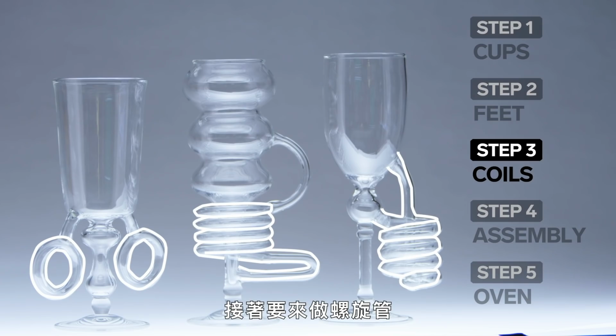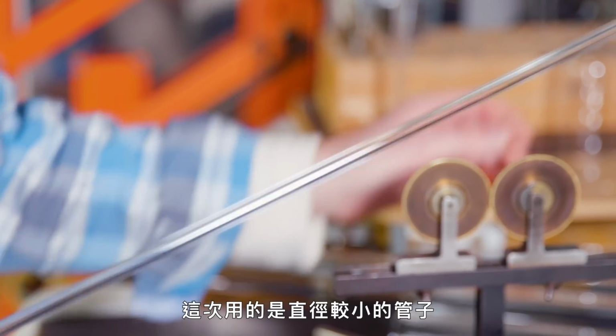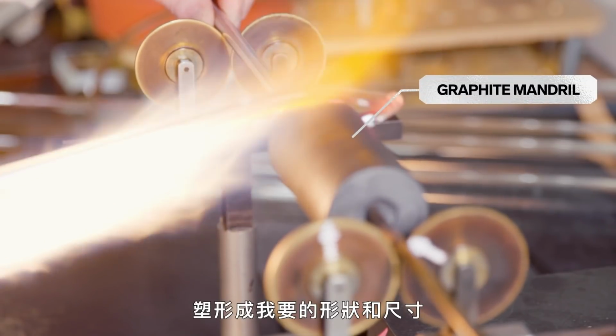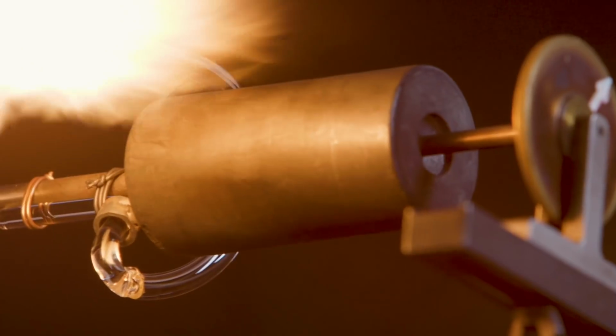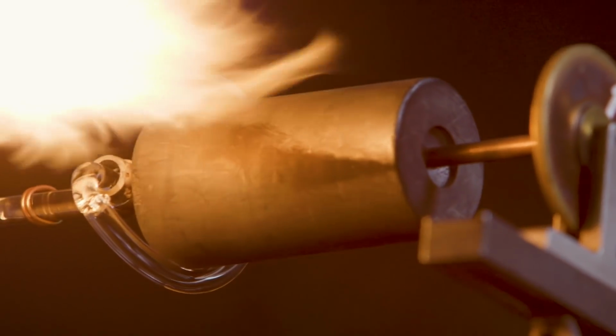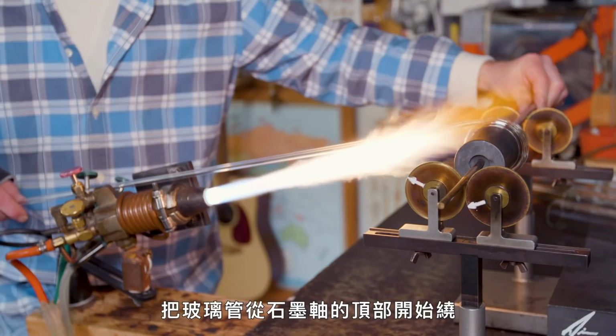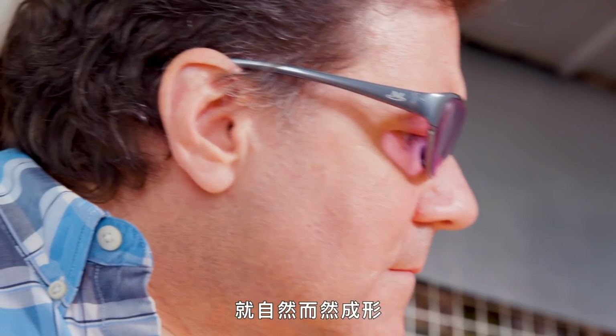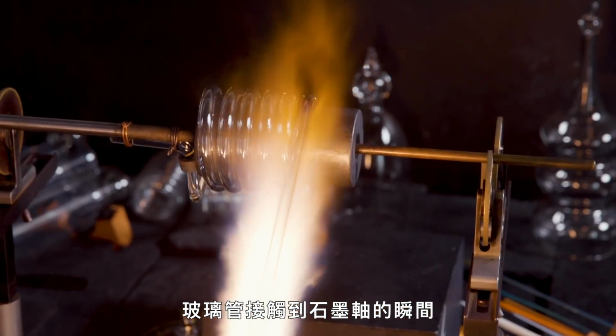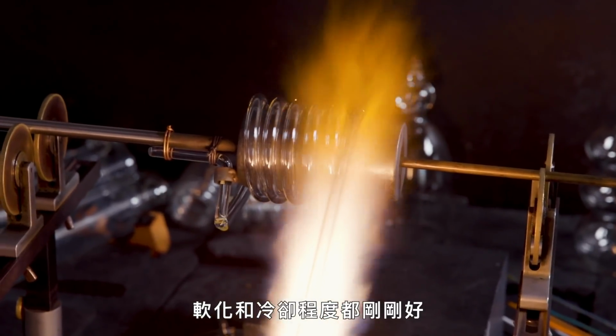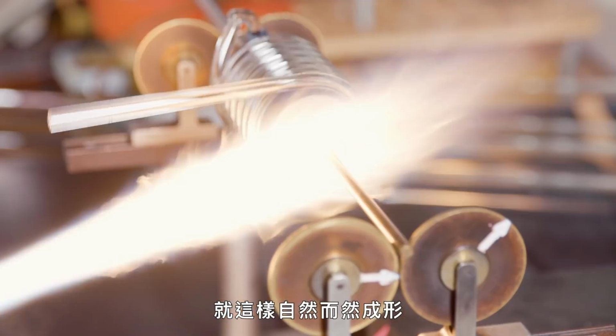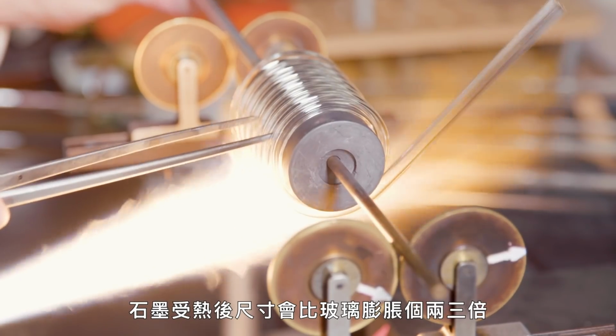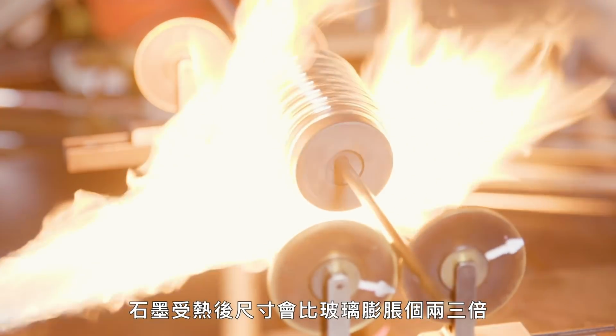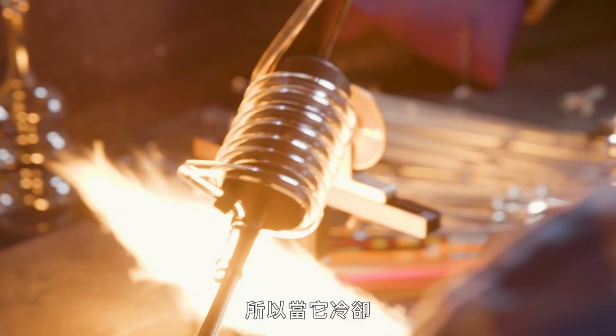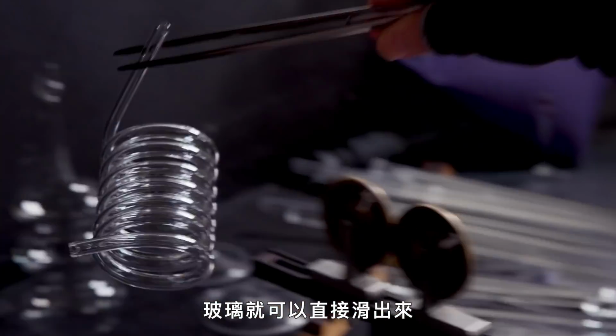Next, we're going to wrap some coils. I'm using a smaller diameter tubing and I'm wrapping it around a graphite mandrel to give me the shape and size that I want. You're feeding your tubing in over the top of the mandrel and everything comes together. It is almost magical because the tubing is just soft enough, cools enough when it touches the mandrel, and it just happens all by itself. The graphite expands probably 2 to 3 times farther than the glass does. So as it cools, it's going to shrink twice as much. It will shrink down and allow the glass to slide off.